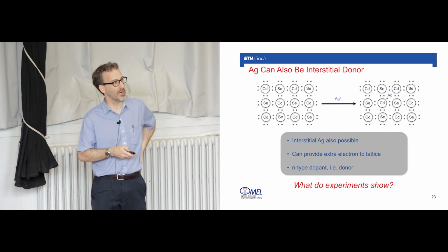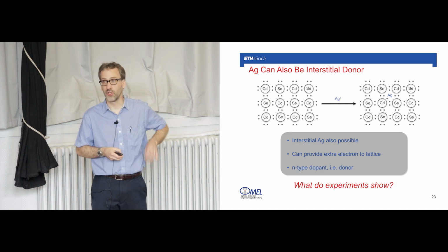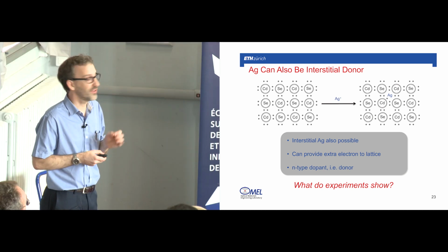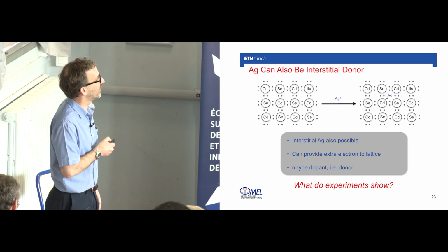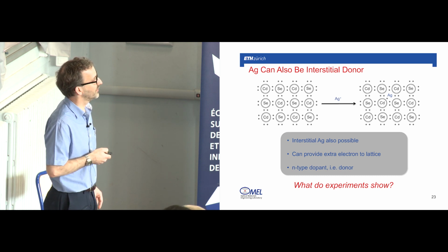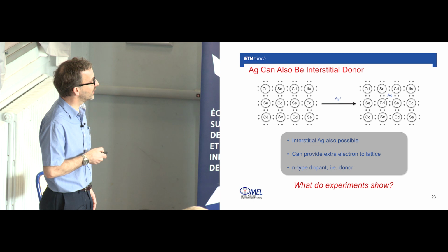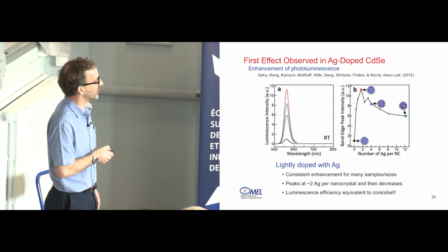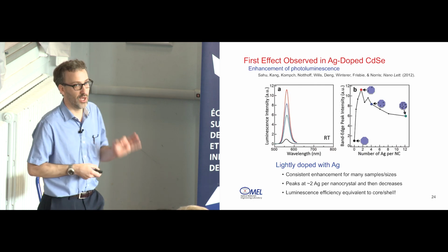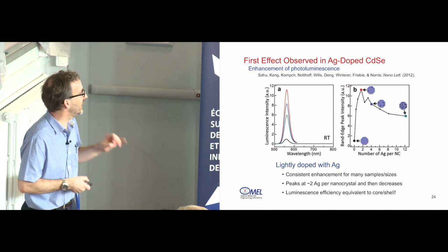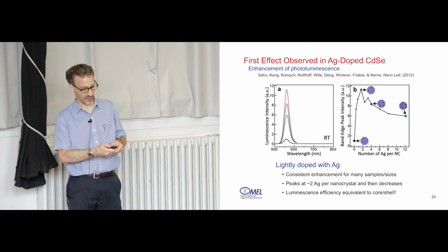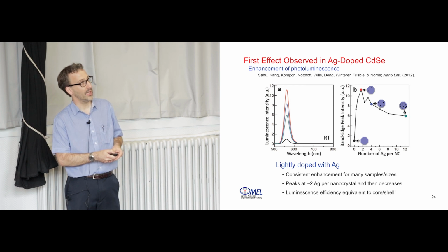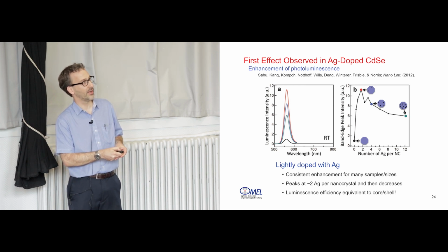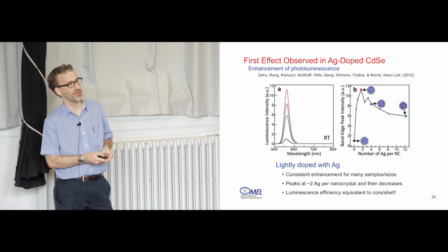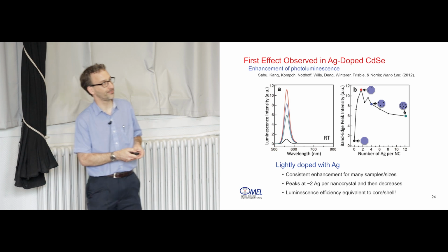I'm not going to show you all the experiments due to time, but I want to show you one of the really puzzling things. One of the first things that Ayash saw is a dramatic enhancement in the photoluminescence with doping. Here is the photoluminescence spectra of these cadmium selenide nanocrystals undoped. And it's not that it's weak, I'm just normalizing it to 1 because it's going to get a lot bigger in a second. And then on the right here, I'm plotting the peak of this PL line as a function of the number of silver atoms per nanocrystal. So this is the undoped sample.